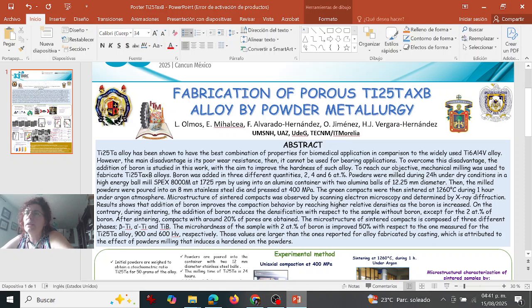So, to overcome this disadvantage, the addition of boron is studied in this work, with the aim to improve the hardness of such alloy. To reach our objective, mechanical milling was used to fabricate the titanium 25 tantalum and boron alloys. Boron was added in 3 different quantities, 2, 4, and 6 atomic percents. The powders were milled during 24 hours under dry condition